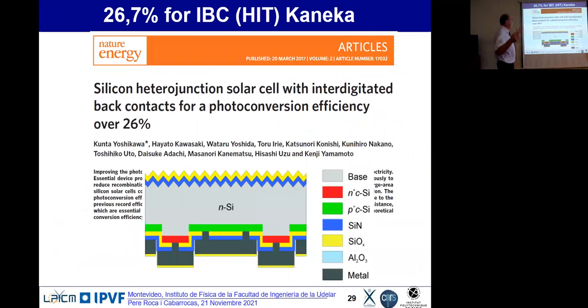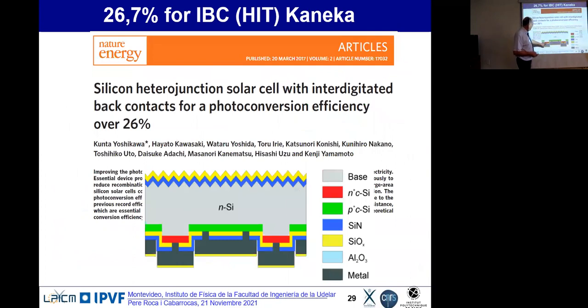The optimum would be to make interdigitated back contact. Most of the cells you see everywhere have contacts on the front and on the back. Of course, if you have contacts on the front, you have reflection losses. From the optical point of view it's not the best, because when you have the fingers, the light doesn't go through, so you have optical losses. Ideally, you would like to have the N+ and P+ contacts on the back of the cell, nothing on the front. And that's what SunPower developed in the 80s.